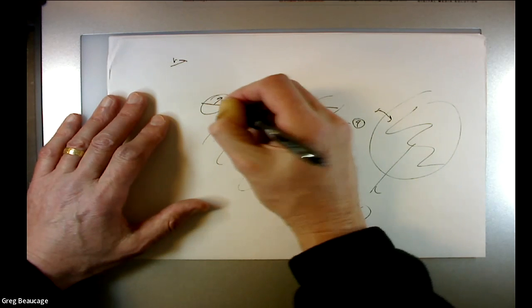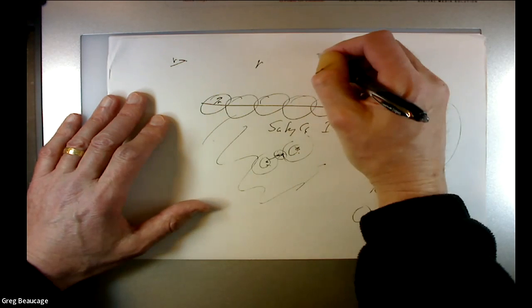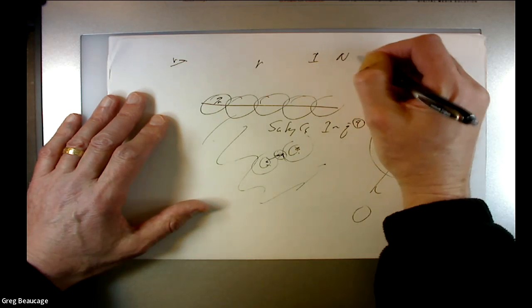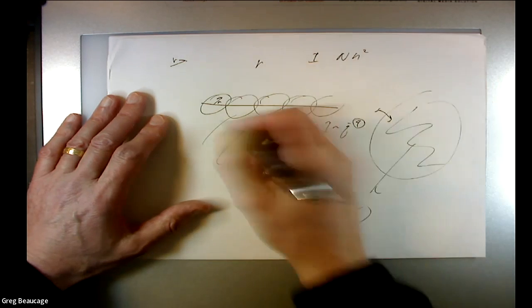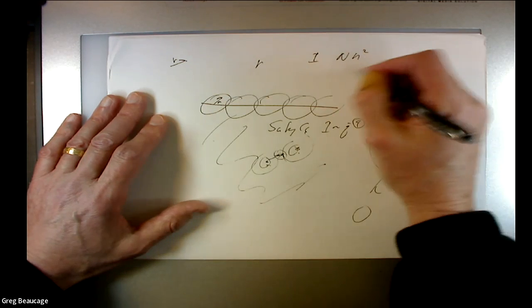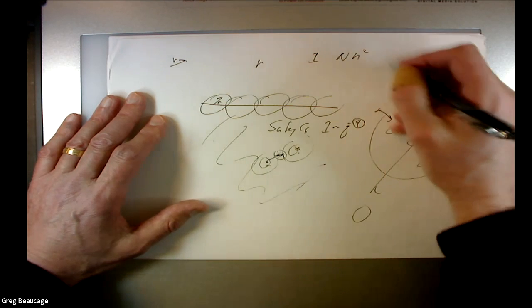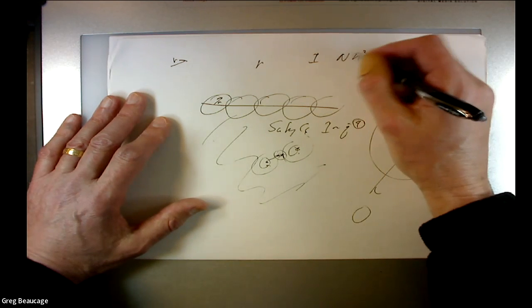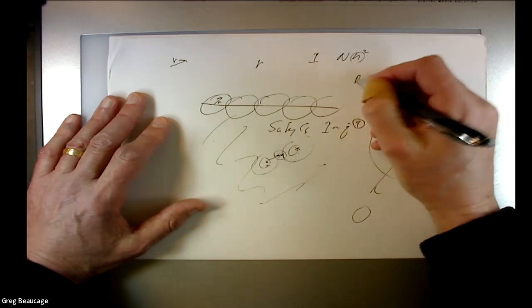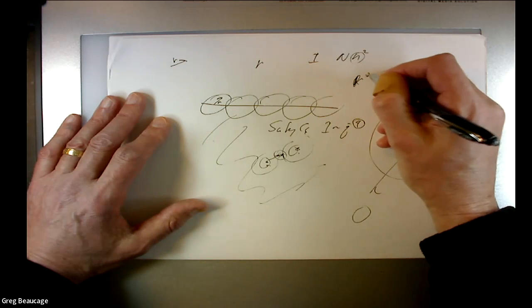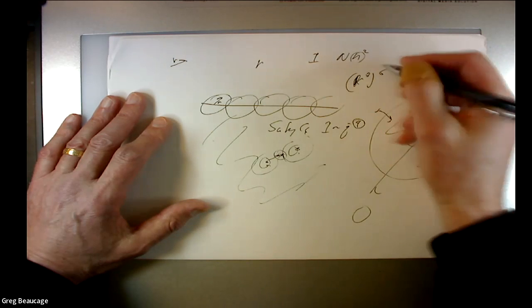So anyway, you can find that if the surface is made up of spheres of size r on the surface, the intensity is going to be how many, times the contrast squared. The contrast is going to be the volume of that thing squared. So it's the small r cubed, and it's squared, so it's r to the 6.